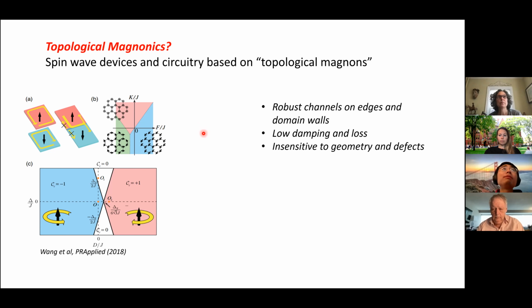This is actually different from electronic band structure. For electronic systems, you can have these Weyl semimetals, where the low energy physics always happens at zero energy, so you can have non-trivial topology at zero energy. But for magnons, the band is always gapped for a stable magnetic order, so it corresponds to the case of electronic systems where all the filled bands altogether have trivial topology. So in that sense, the magnon topology talked about today is a subclass of electronic topology.